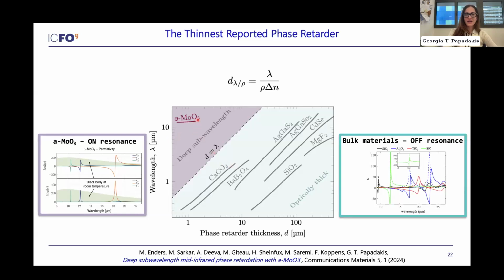By contrast, here you can see in the red line, the regime of operation of molybdenum trioxide as a half-wave plate, where we actually operate at the resonance. So in fact, we operate where the material absorbs heavily, but because the birefringence of this material is gigantic, the material can be extremely thin. So even if it's lossy, it actually remains transparent.